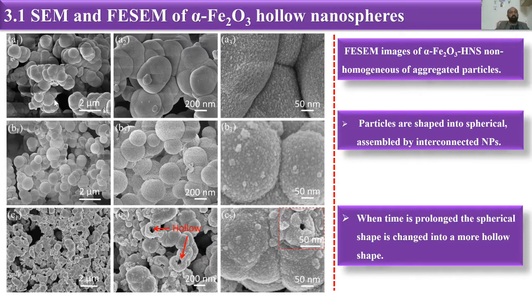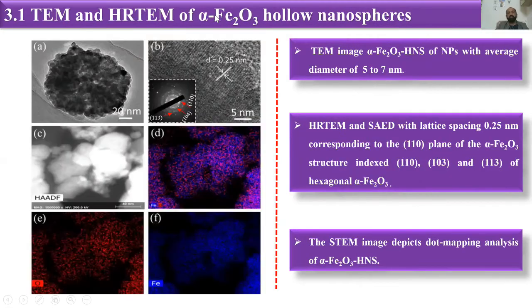So we have done the TEM and HRTEM of our hollow nanospheres, and we have done the SAED and HRTEM, which correspond to the hexagonal structure of our system. And we have seen that in the mapping which we got from the STEM, we find the uniform formation of our alpha hollow nanospheres.